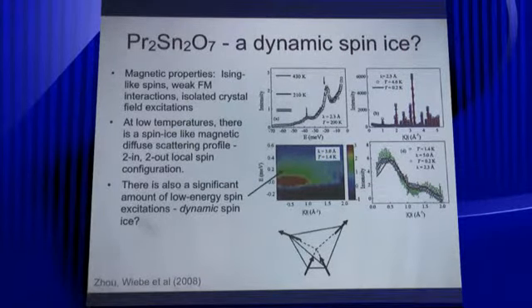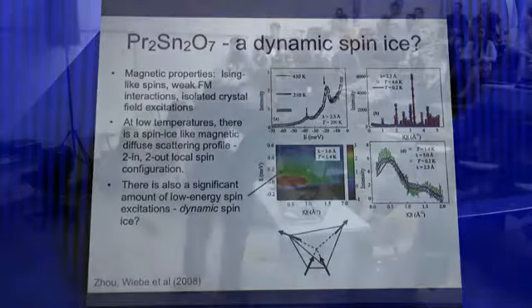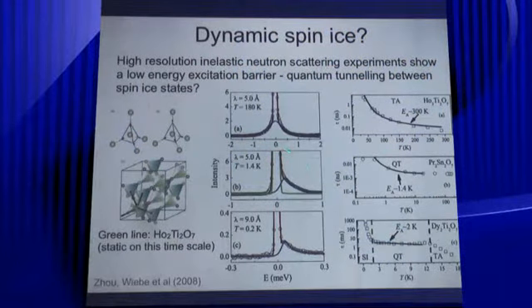So we called this the dynamic spin ice when we published this paper. In the same paper, we did some high-resolution neutron scattering measurements. If I can direct attention to this middle plot here, the green data is holmium titanate. So you can see it's really static on this time scale. The praseodymium stannate has this unusual low-energy spin fluctuation, and we extracted a characteristic time for that so we can compare it to its AC susceptibility measurements.